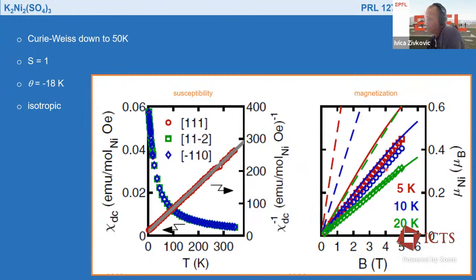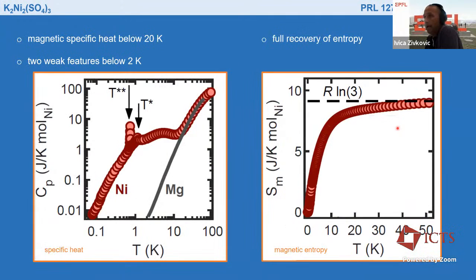And then if you look at the behavior in the magnetic field, you see that these points at different temperatures deviate significantly from the Brillouin function, which is given by dashed lines, but also they deviate significantly from the solid lines, which are the results of the classical Monte Carlo calculation, which means that at least partially there is a significant contribution from quantum renormalization. If you look at another thermodynamic property, specific heat, here we have a comparison with a parent compound, the magnesium one, a non-magnetic analog, and you can see that there is a strong deviation from the purely phononic behavior below, let's say, 20 Kelvin, which agrees with the Curie-Weiss value. And if you integrate all that, you basically recover the whole expected entropy in this compound.